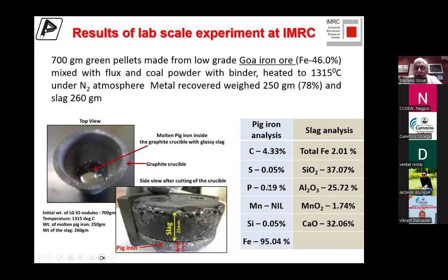Phosphorus was a little higher because the content in the Goa iron ore was significantly higher, and of course we were able to recover a lot. Here you see a lot of silica. SiO2 is about 37%.